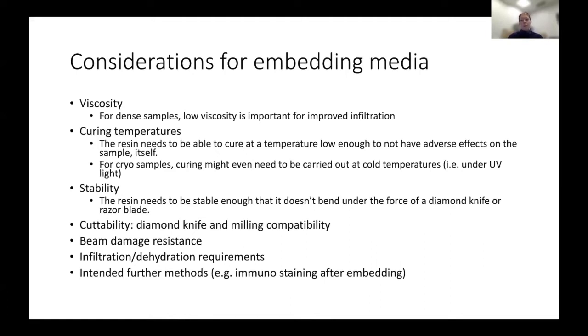So when you are considering choosing a resin for your project, you'll want to consider a few different characteristics. Different resins will have different viscosities. Some of them infiltrate into samples much better than others. Unfortunately, the ones that infiltrate very well don't necessarily resist beam damage better. So if you're working with a dense sample, you might consider opting for a lower viscosity resin to make sure that it infiltrates your sample better. Otherwise, you can go with a higher viscosity resin and emphasize a different characteristic that you might be more interested in.